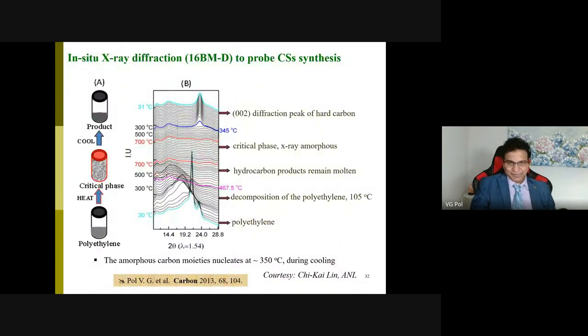We did a lot of science behind it to understand how we are developing this material. So we took the small reactor and put it in front of the X-ray. We have the Advanced Photon Source, which is a high energy X-ray. And it is showcasing in this plot how you are converting this plastic waste all the way to carbonaceous material. So we started at room temperature, we heated to 700 degrees Celsius. We waited there, nothing happened, and then we started cooling down. So this is the way we understood the mechanism of formation of the material, and we understood that around 350 degrees Celsius during the cooling, we make this carbonaceous material.